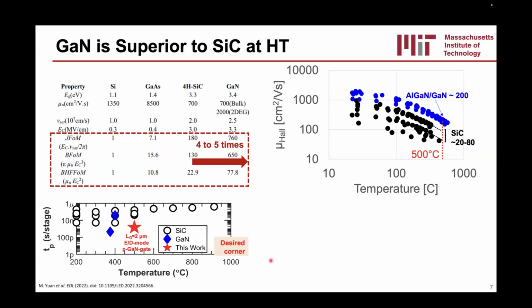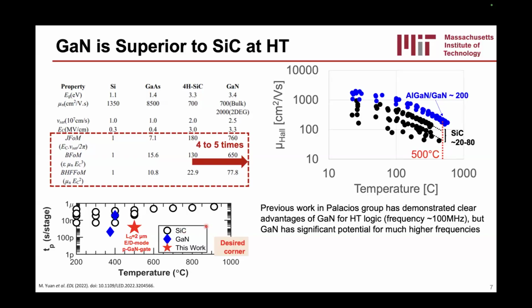There's been previous work in our groups, specifically from Dr. Ming Yuan, on demonstrating that you can make a GaN ring oscillator and operate at 500 C. And you can get about an order of magnitude improvement from an equivalent silicon carbide ring oscillator. That being said, these devices that were made here were relatively slow in the grand scheme of things. They were fairly long channels. And so their frequency range was in the 100 megahertz range.